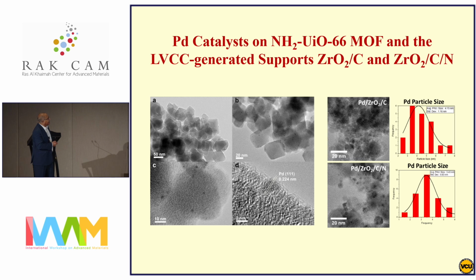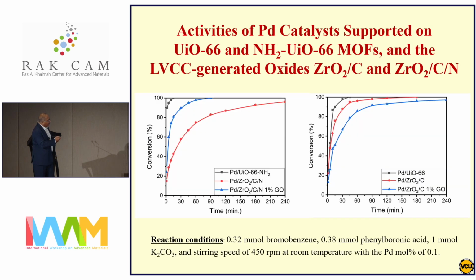Then we go and look at the activity, and we see, as I mentioned, if you start with the MOF by itself, which is here, this is the amine MOF, palladium on UiO-66 amine. Again, the reaction is complete within 2 minutes, 100% conversion. But it's a homogeneous system. It's not recyclable. You cannot separate this, and you cannot repeat this experiment. It involves ions, mostly ions.